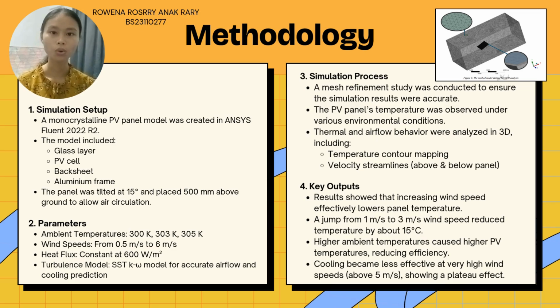The result showed that increasing wind speed from 1 to 3 meters per second reduced the panel's temperature by around 15 degrees Celsius. However, cooling became less effective beyond 5 meters per second, showing a plateau effect. On the other hand, higher ambient temperature consistently caused the panel to heat up more, lowering its efficiency. So, that is the overview of the methodology used in the study.